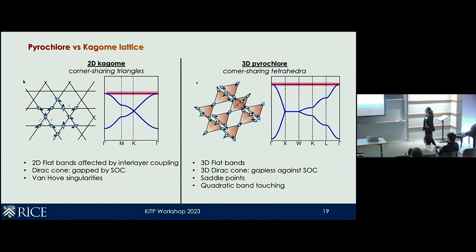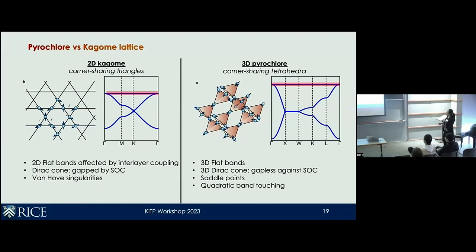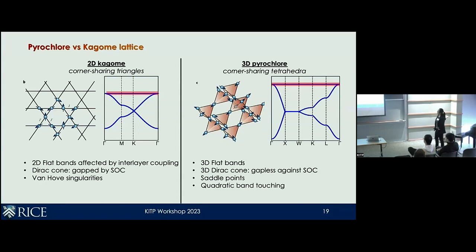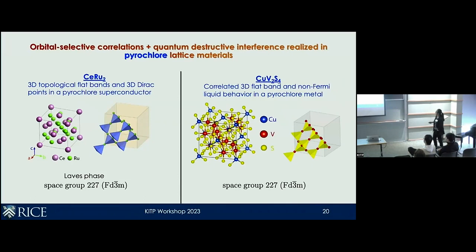As a brief summary, comparing Kagome and pyrochlore side by side: in the pyrochlore, the flat bands are flat in three dimensions and the Dirac points remain gapless, in contrast to the Kagome system where they are gapped by spin-orbit coupling. In the Kagome system the saddle points are Van Hove singularities in the 2D theoretical model, while in the pyrochlore they remain saddle points without divergent density of states. In addition, there is a guaranteed quadratic band touching associated with the pyrochlore lattice. We have demonstrated that the pyrochlore lattice is a good host for topological flat bands.